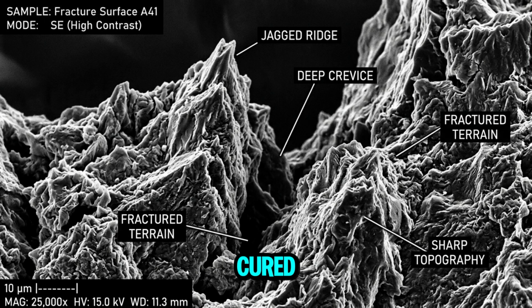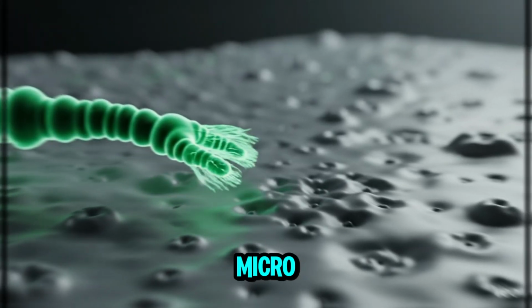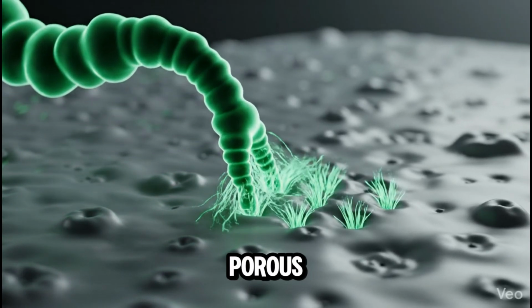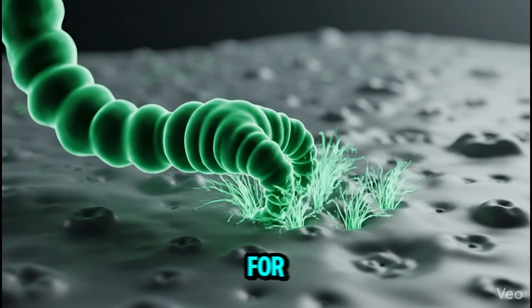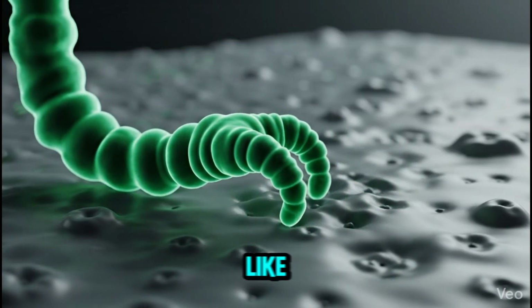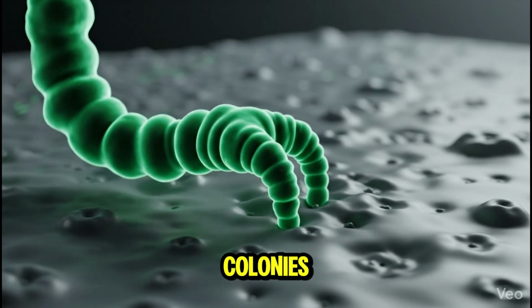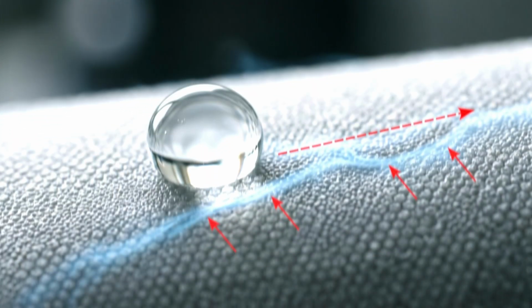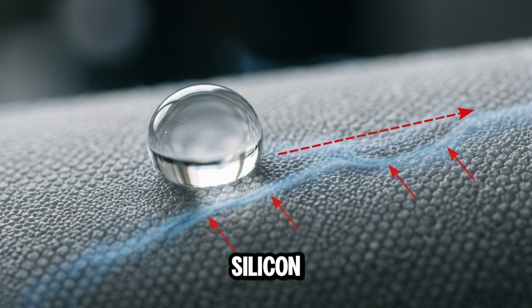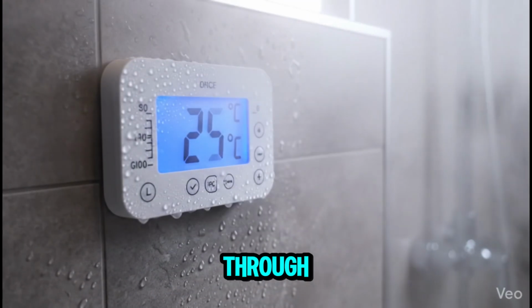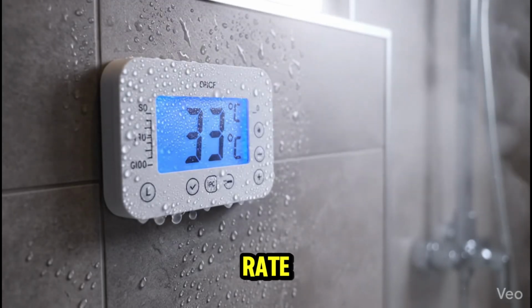The surface of cured silicone, examined under electron microscopy, is not smooth. It contains microcavities and a slightly porous texture that provides purchase for fungal hyphae, the thread-like structures that allow mold colonies to grip and expand. More critically, silicone is permeable to water vapor. Not to liquid water, it repels liquid water well, but water vapor diffuses through cured silicone at a measurable rate.